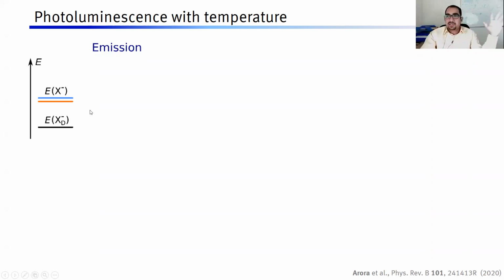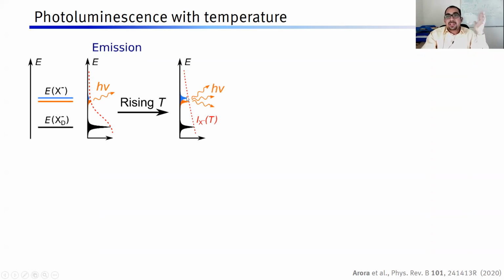Once the trions are created, they will have a Fermi-Dirac distribution. So these higher states, which are bright states, will be less populated with the trions because they are at higher energy, and this state will be more populated. So you can expect a little bit of emission. But once you raise the temperature, the emission should rise.